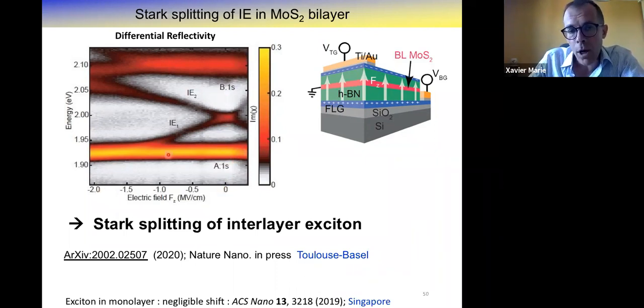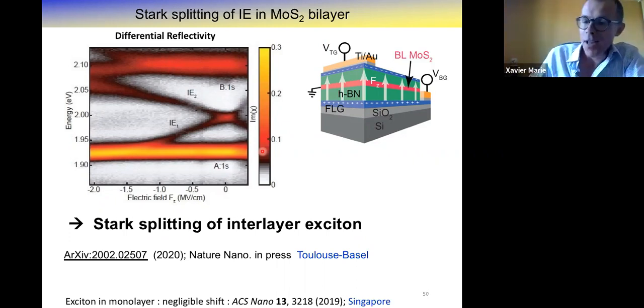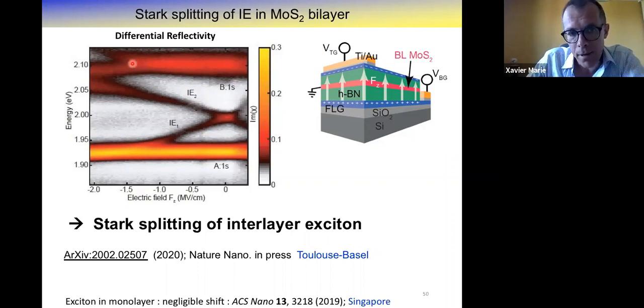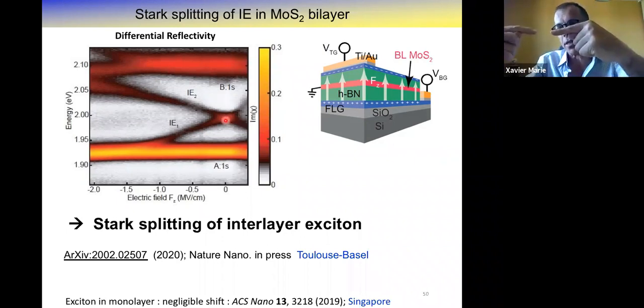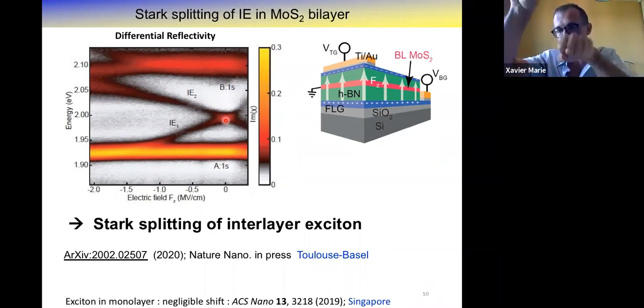Then we apply the Z field. For the A 1S exciton, no change, no surprise. It has a very, very weak dipole moment, almost zero. So the electric field has almost no effect on the A exciton. The B exciton is more or less the same, except at the end, if I have time, I will comment. But for the interlayer exciton, as expected, initially I have two degenerate interlayer excitons, one with the electron at the top, and the other with the electron at the bottom.